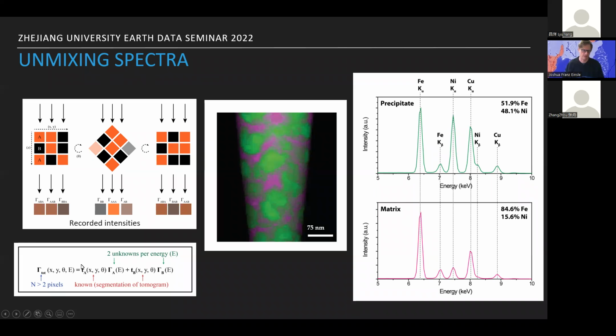And by assuming that we only have two unknowns, and for a total of over 30,000 pixels through the tomographic volume, you can see we have a very largely overdetermined system. By running this thickness map analysis on the tomography, based on how we segmented the data set, we were able to get a composition for the precipitates, i.e. the tetrataenite particles, of 51.9% iron to 48.1% nickel, which is in line with accepted values for tetrataenite. And the matrix came out to be 84.6% iron to just under 16% nickel.